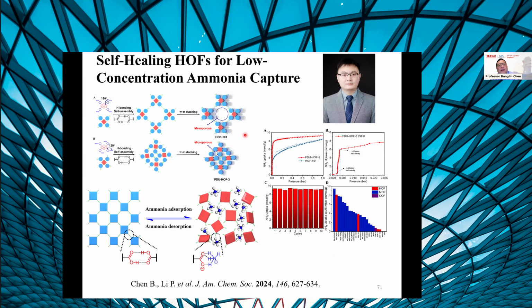And recently, my former postdoc at Fudan University developed this structure. Again, it's a dimer, and uses this organic linker. The pore space is smaller, and even under low pressure ammonia concentration, the material takes a large amount of ammonia, and this framework and ammonia recognition can be reversible. So this is a very amazing material for ammonia capture.